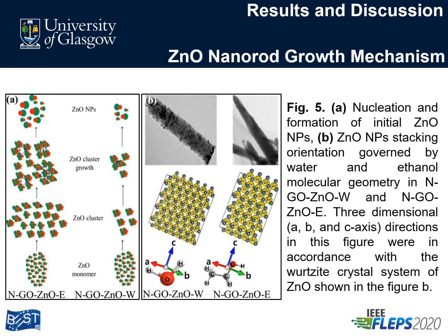Herein, it is important to note that the monomer formation in both cases was strongly enhanced by the presence of different nitrogen configurations. This has altered the electronic environment of graphene oxide, enhanced the system reactivity, which led to the generation of a higher number of monomers, which accelerated the nucleation rate and finally produced small particles with narrow size distribution. However, the eventual survival battle of a monomer is with the dielectric constant of its solvent, which determines the final number of nuclei for growth.